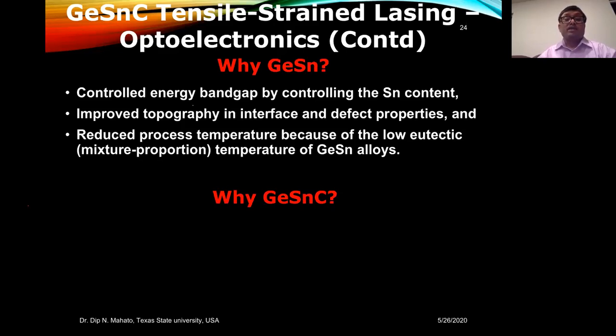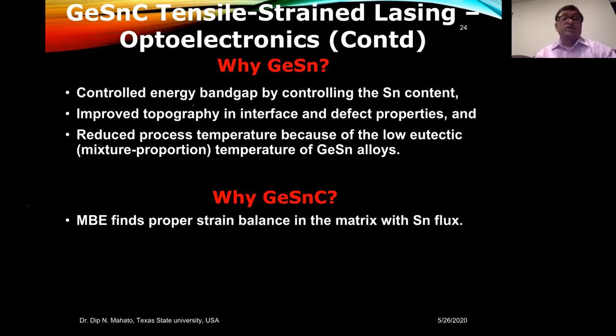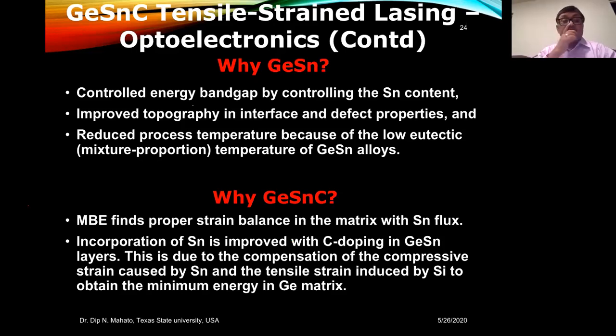But then why carbon? We dope with carbon, so molecular beam epitaxy finds a proper strain balance in the matrix with the tin flux that you shoot in the molecular beam epitaxy. Another thing is that this provides improved incorporation of tin when you dope with carbon in that matrix. This is because of the compensation of the compressive strain caused by tin and the tensile strain induced by the silicon, to obtain the minimum energy in the germanium matrix.